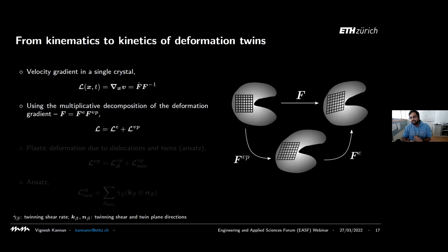So for those of you who have not done courses in continuum mechanics, I promise to give you a little punchline of what these equations mean. I'm just going to give you a little detailed introduction of how we can address these kinds of questions. This comes from the area of crystal plasticity where you have a single crystal. You apply a particular deformation gradient F to it, and you can separate that into elastic and viscoplastic components. So you have a multiplicative decomposition of your deformation gradient.